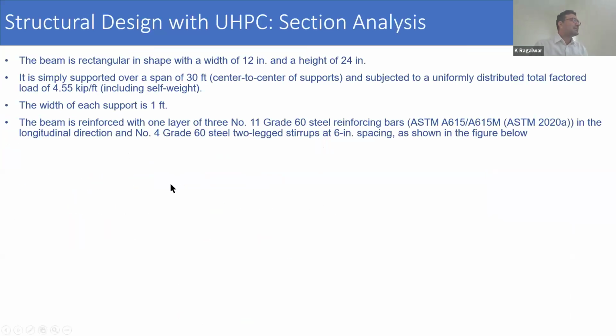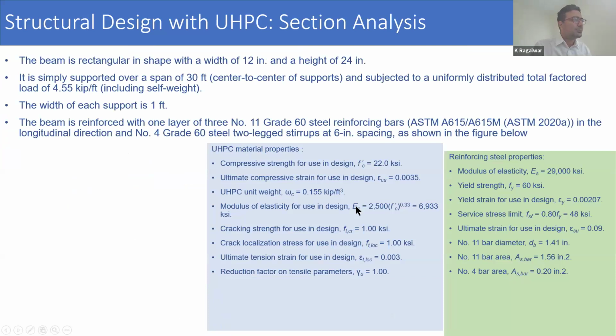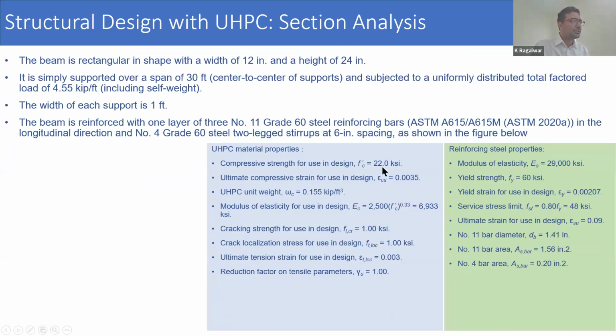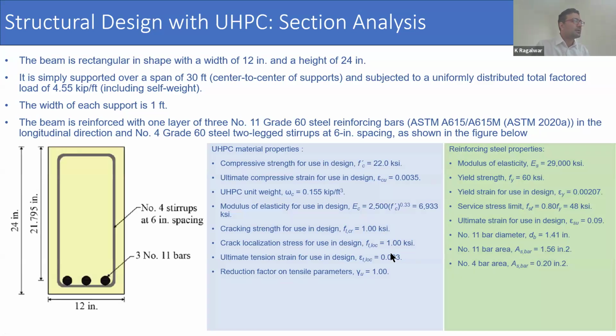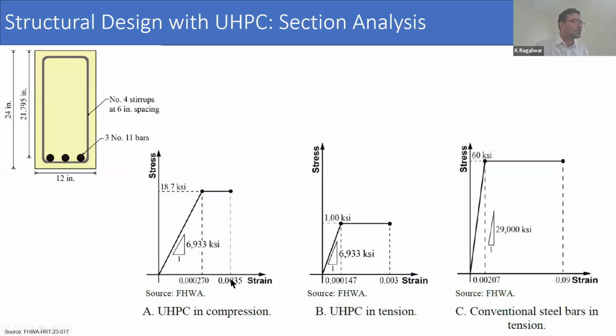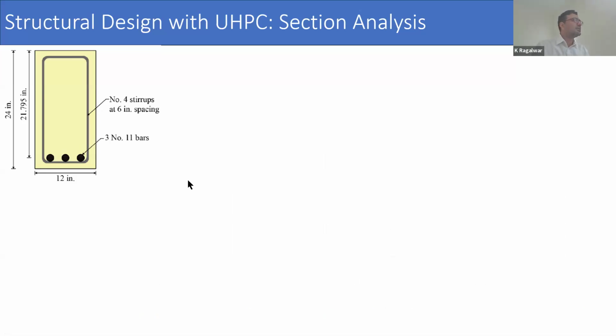Now we'll look at section analysis. I have taken typical parameters here, which are shown. A compressive strength of 22 KSI, and typical steel reinforcement properties. Important to note here is the first cracking strength of 1 KSI, similarly a localization stress of 1 KSI, and a strain of 0.003. So these are the models. You would see the compressive strain limit at crushing is 0.0035, and then it is capped at 18.7, which includes the factor of safety. And similarly, the strain model for tension.